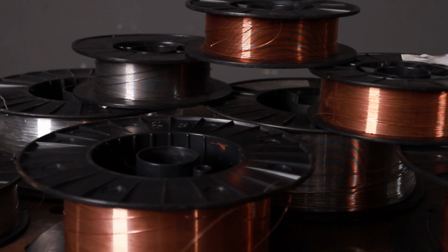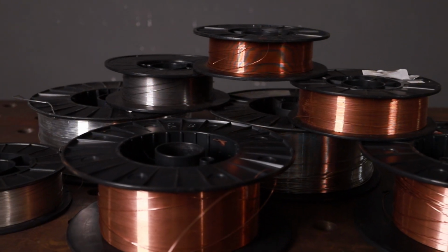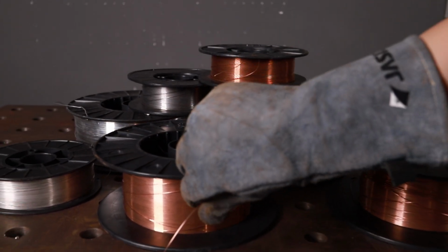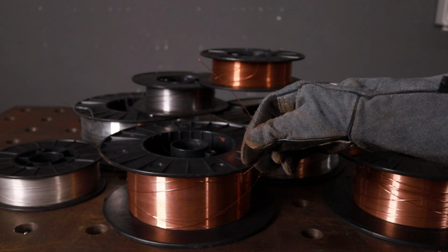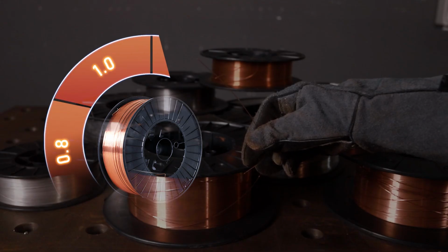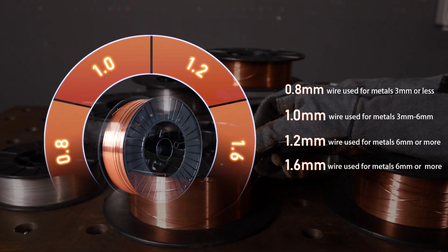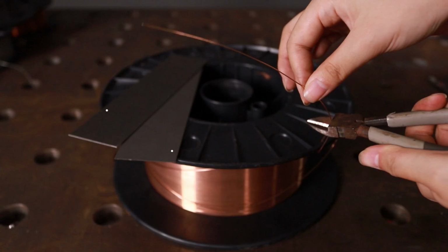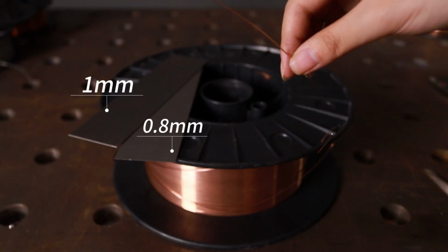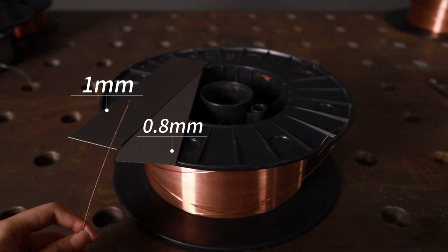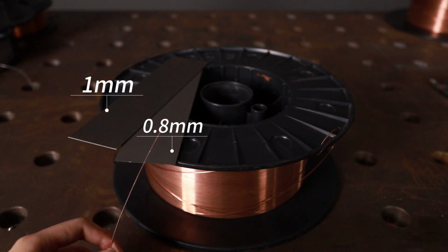First, select a smaller diameter wire, typically between 0.023 inches and 0.030 inches, especially when welding thin mild steel. Smaller wires require less amperage, giving you better heat control and a more focused arc. We're working with 0.8 mm and 1.0 mm mild steel, so a 0.8 mm wire is perfect.